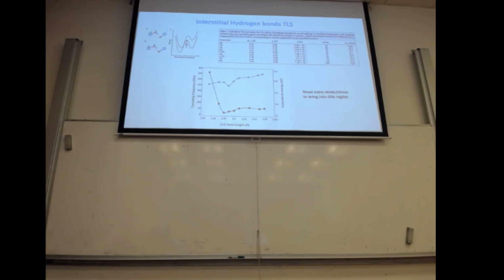But then let's see what happens for these interstitial hydrogen bonds. With these hydrogen bonds, first of all you need to find a configuration. But then once you find the configuration, you have the same problem: you need to introduce some compression in your system, because again, the typical energy scale that you have is very high. And so this comes to a very important point, that somehow the two-level systems that we are dealing with are two-level systems that are strained.